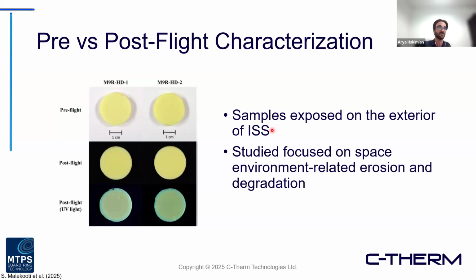And in this case, very novel case, these materials, these aerogels, were actually placed on the exterior of the International Space Station, and then through multiple trips, then returned and tested, of course, tested before they left, and then tested after to see how the material properties changed from those exposed conditions.